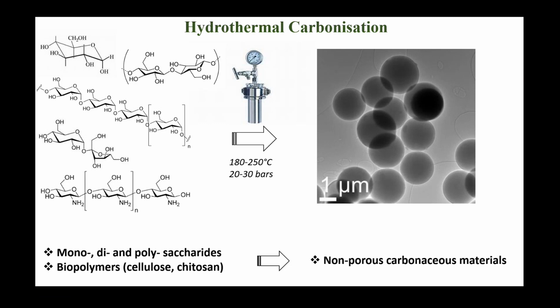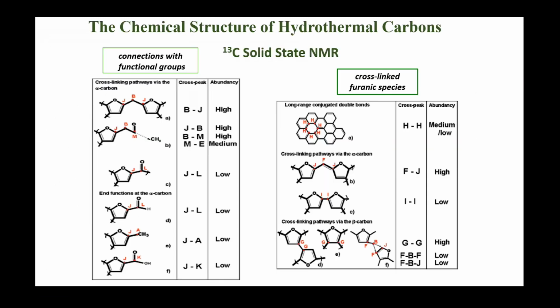So as I said, it helps to have carbohydrates, and that's because if you look at the chemical structure of these hydrothermal carbons, and I also did back in the time a lot of solid state NMR studies to try to understand what they are made of, you will see that they are mostly made of furan rings that are connected together, either conjugated together or linked by aliphatic linkers. They are also terminated with some oxygen-rich functionality, such as carboxylic groups or aldehyde groups. And you also have a smaller fraction of long-range conjugated aromatic molecules. The chemical structure you can tune by tuning the precursor and the temperature at which you do this hydrothermal carbonization, and whether you add a catalyst or not. So it's quite a tunable process.